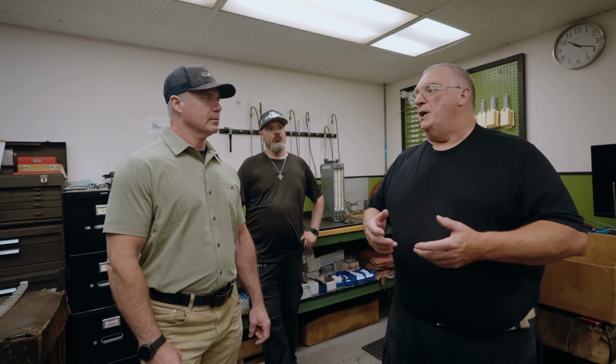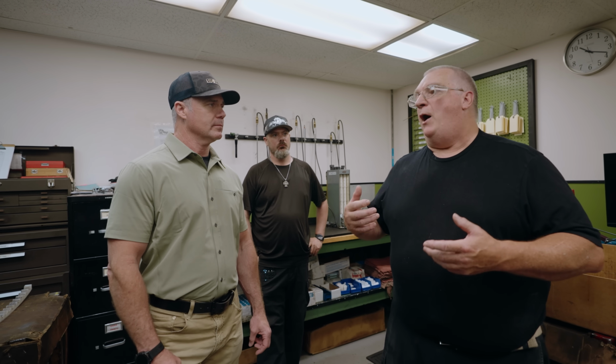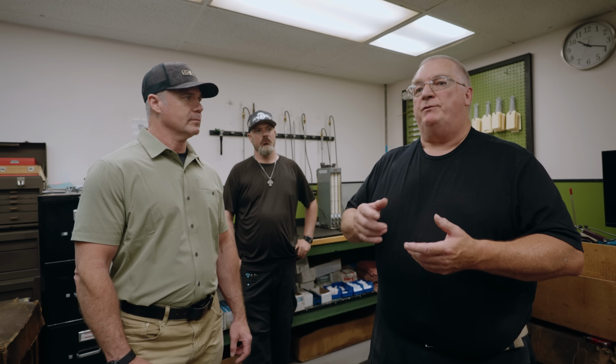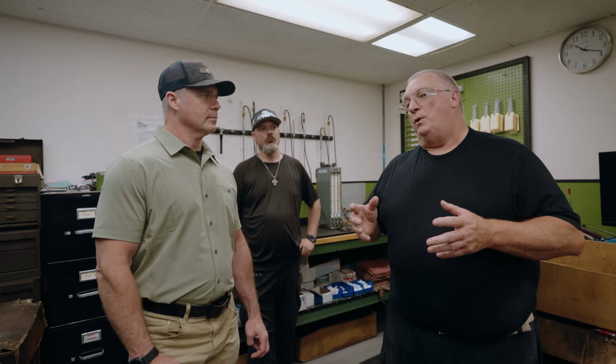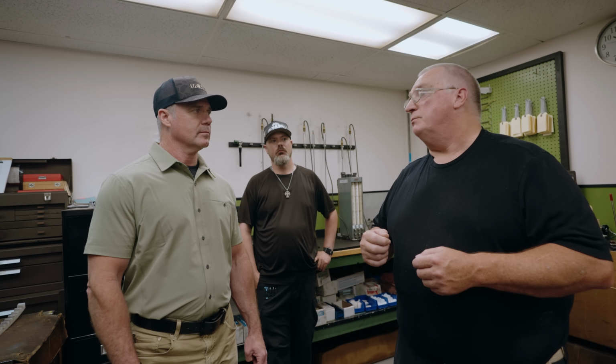Yeah. Most of it is done down the other end of the shop at the hone station and at the reaming station, and then our buttons. We have defined the button itself so that the button gives us the best quality barrel. We have the best interference of it and the best tolerance that are in there. That button, when we're done with it, it gets through a heat treat, it gets in here again. We're within 3 to 4/10 from end to end of that barrel, which is phenomenal.